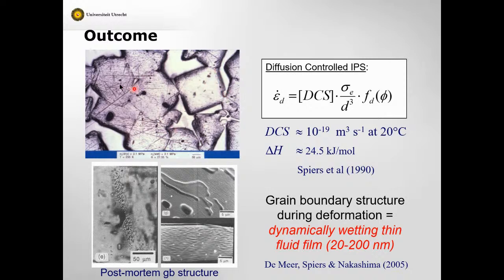Here they are, like absolutely certain evidence for this process of pressure solution, stress-driven dissolution and reprecipitation. We compared our results with our models, and the fit was extremely good. We got a very, very close correspondence with this theoretical law, strain rate linearly proportional to stress, inversely proportional to grain size. Fitting the model to the data allowed us to quantify this grain boundary property.